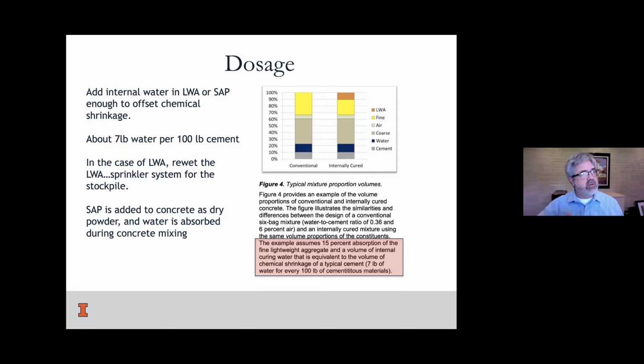Would this work to be dispersed in a truck if we did it that way right at the time of delivery of the concrete to the site? And our sense is that that's probably the best way to go, is to add it as an admixture into the truck right before using. And so when you do that, of course, you're going to get some effects. One effect is that you'll get slump loss. And we'll talk about that in a minute.